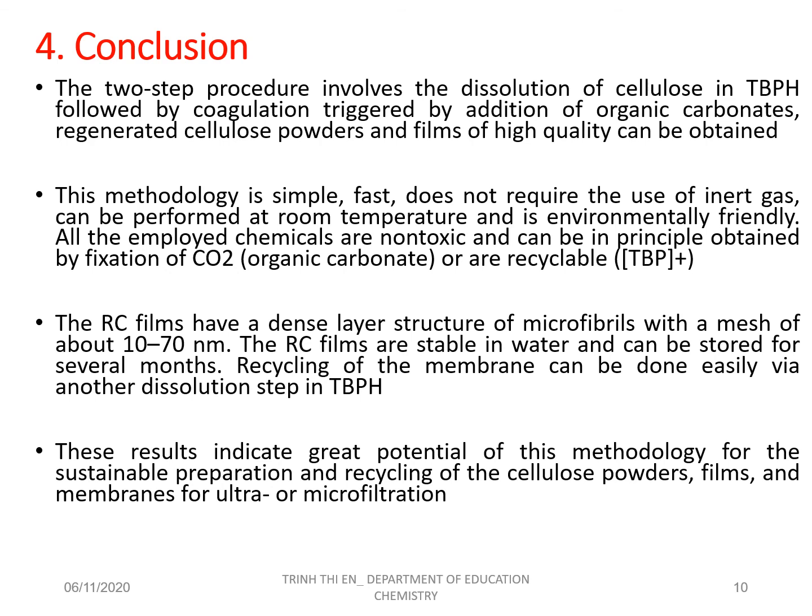recyclable. And the RC film has a dense layer structure of microfibrils with a mesh of about 10 to 70 nanometer. The RC films are stable in water and can be stored for several months.